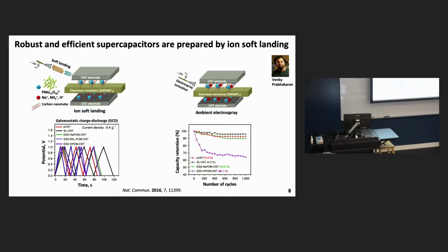If you look at these charge-discharge curves, this basically represents how much energy these supercapacitors are able to store. And you can see here that the soft-landed device had a much higher charge storage potential than the devices prepared using drop casting or electrospray deposition.